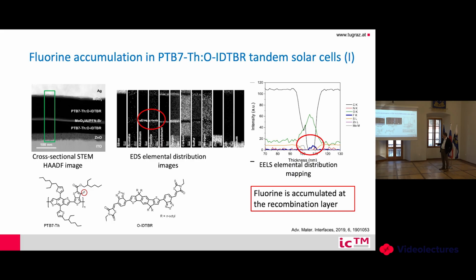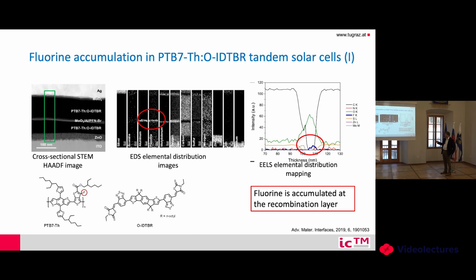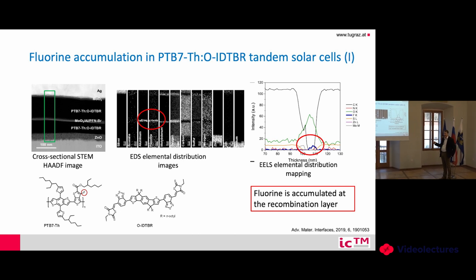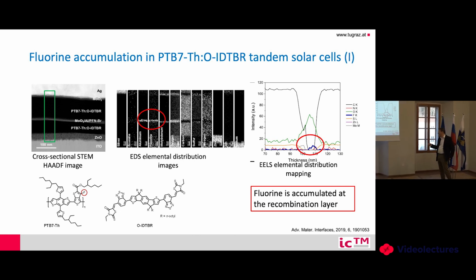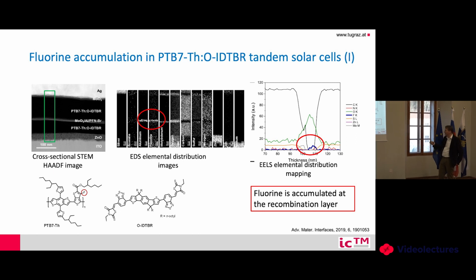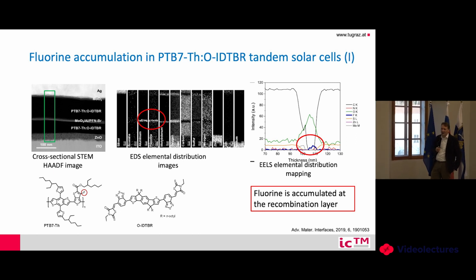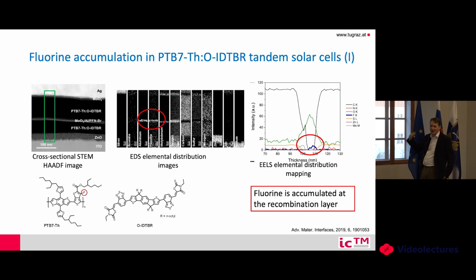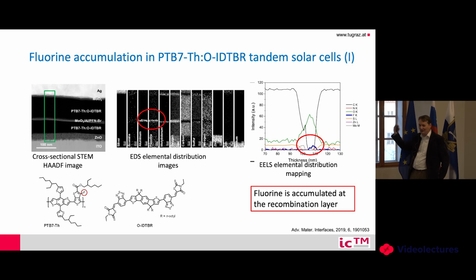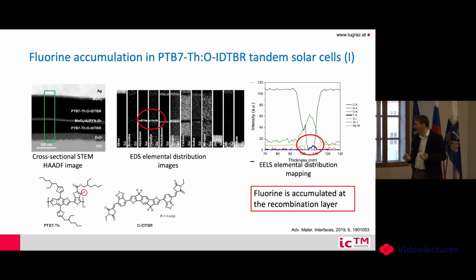But what we found out is that in this layer where we have aluminium, we found also a lot of fluorine. That means that the organic fluorinated compounds are not stable in combination with aluminium. So there are also some other issues with the stability of organic solar cells, which are at the moment not totally known. Yeah? So there are also some other issues which have to be resolved. With silver, it's much better. Yeah? So silver works better, but of course it's also more expensive.